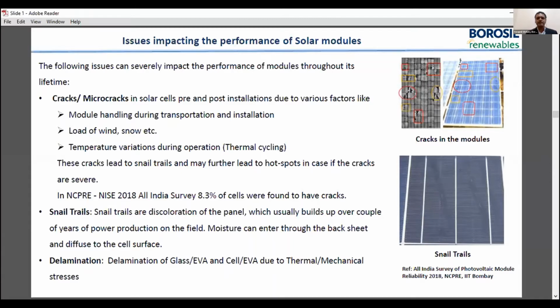performance of the modules. Then there are snail trails, which is basically discoloration of the panel. This happens typically over a period of, let's say, 2 years, and then power production starts getting impacted. There is also another issue of moisture ingress, which I'll come to on the next slide, which happens through the backsheet and then starts impacting the EVA as well as the cells. Delamination, whether glass to EVA bonding or cell to EVA, also happens due to thermal or mechanical stresses. These issues start impacting the performance of the solar module, and they are directly related to the encapsulants, including glass as well as the backsheet.